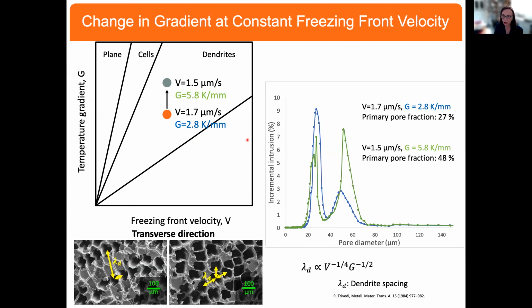And likewise, if I do this for constant freezing front velocity, but maintain the freezing front velocity and alter the gradient, you'll notice we aren't changing size too much, but what we're changing is how much of the main channels we have with respect to the side channels shown here. And that dendritic spacing here is a function of both those parameters, the velocity and the temperature gradient. So let's go quickly to these experiments.